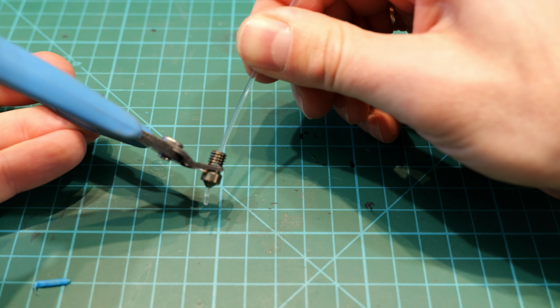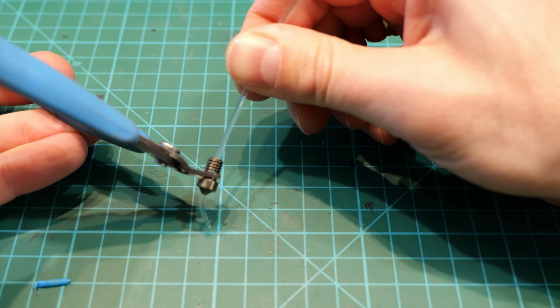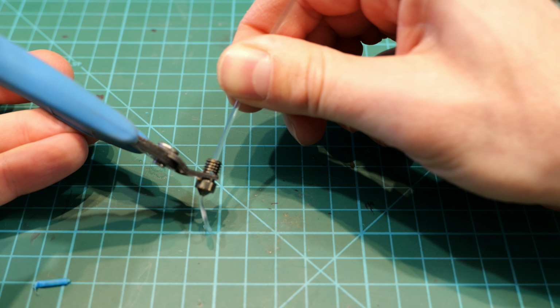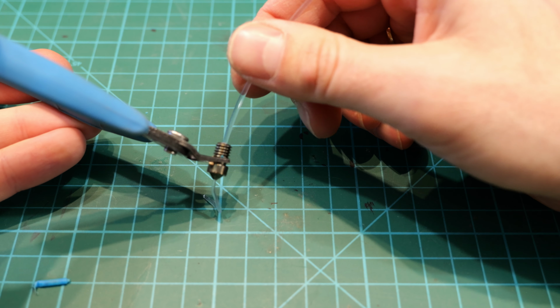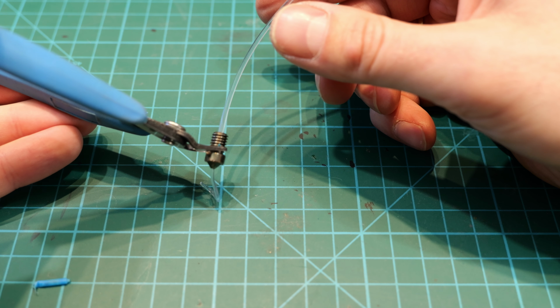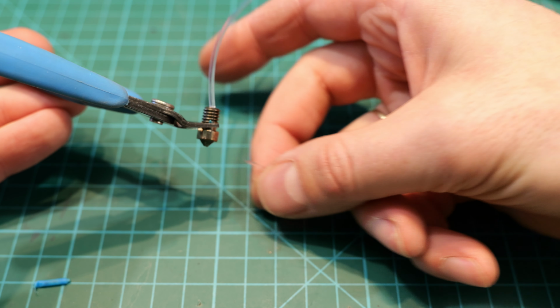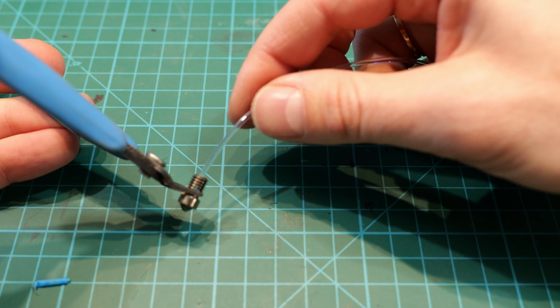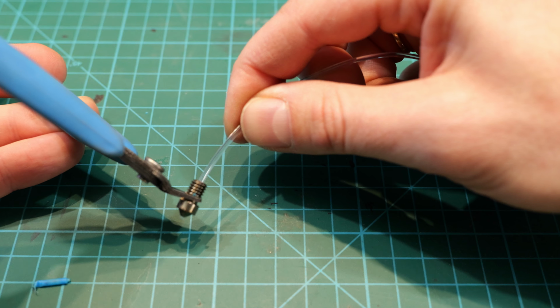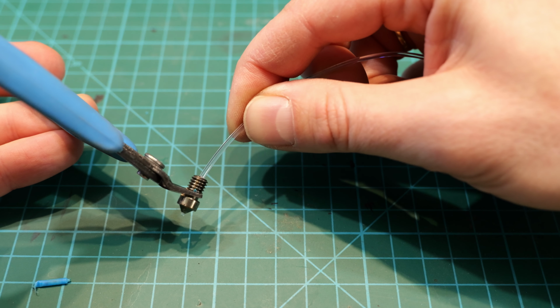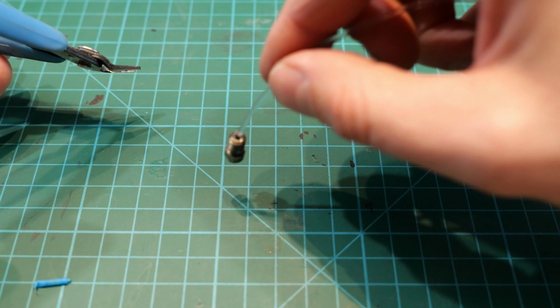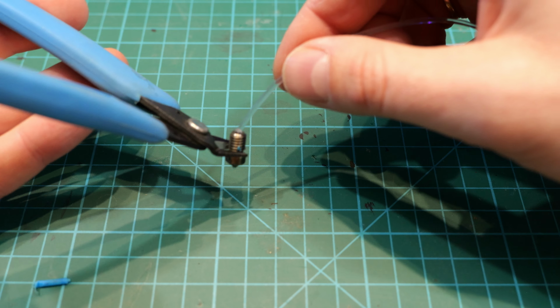Again, grab the nozzle with the pliers. Heat up the nozzle and try to push the PLA through the nozzle until it starts coming out or just stops. Now, wait until it cools down and try to remove the filament while holding the nozzle with pliers. You don't want to break the filament, so sometimes you will need to heat up the nozzle a bit so it's getting soft but it's not melting.